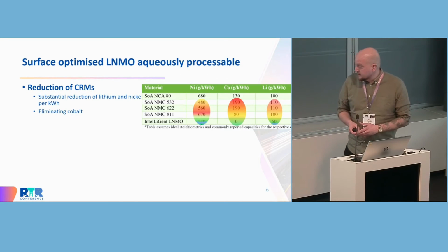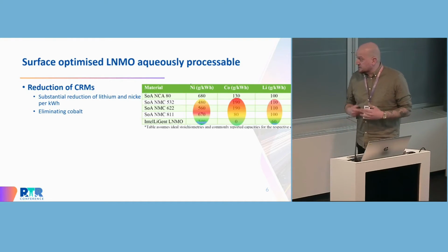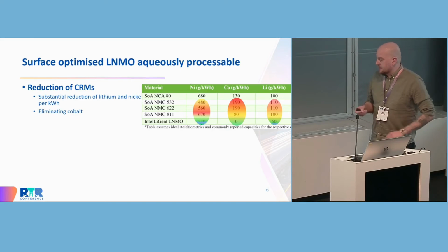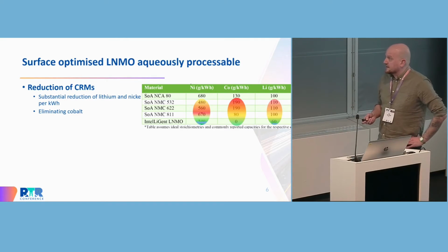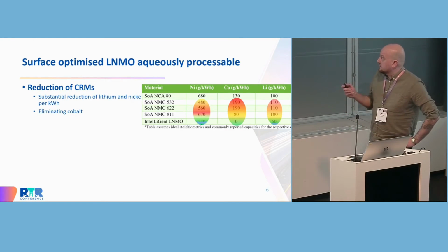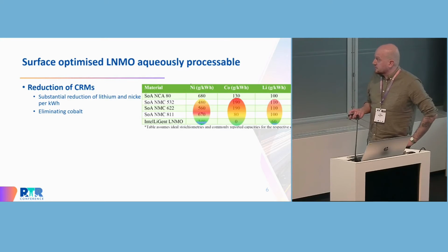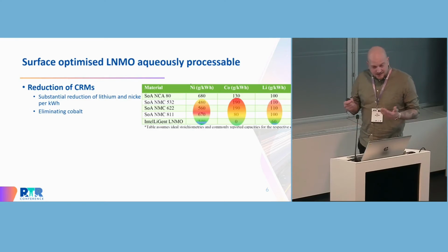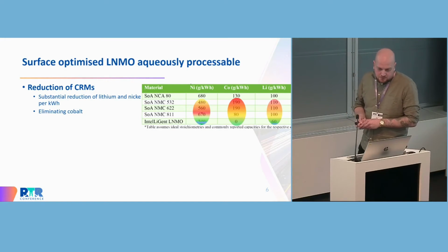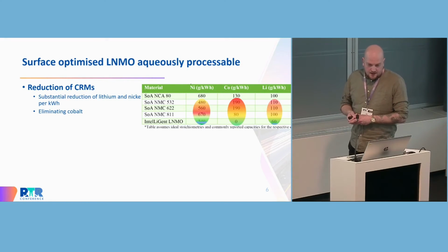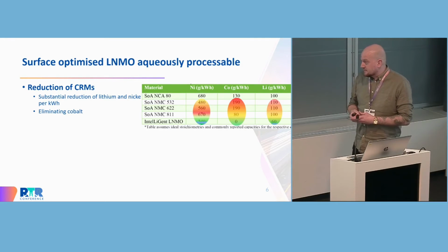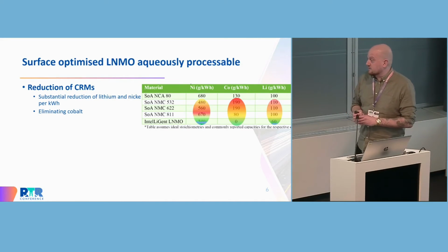I would highlight the sustainability factor here, which we think is very important. And if we compare our LNMO to state-of-the-art layered oxides, we of course see that we are free of cobalt, we know that, and we also are much lower in the nickel content, so it's just a matter of time, in my opinion, that we also run into the same issues with nickel, because we're heavily based on manganese for now, which is hopefully still all right.